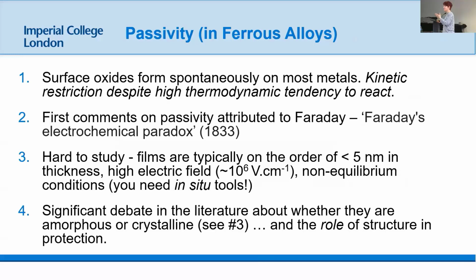So these conditions are very non-equilibrium. You're in an aqueous environment with a high field. So if you form your passive film and then you take it out and put it in an ex-situ scenario, potentially with a high vacuum, you potentially change everything you're trying to measure.